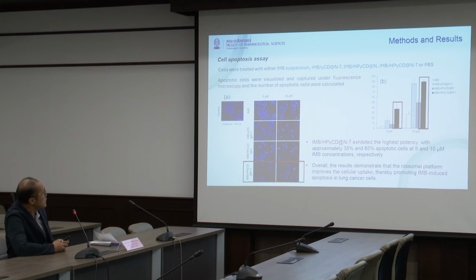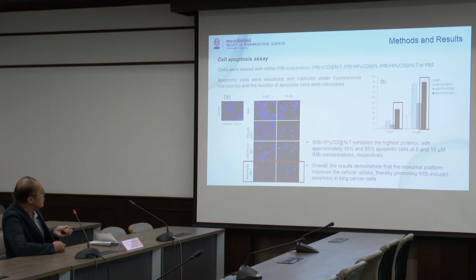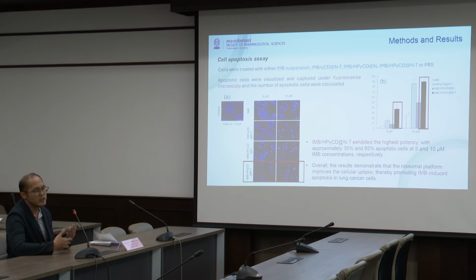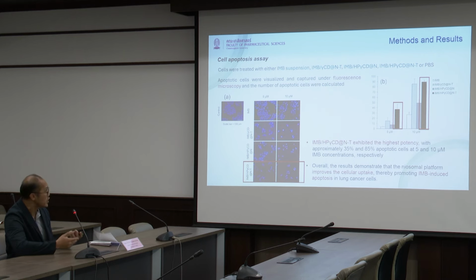And the last one is the cell apoptosis. We can show that in our formulation, especially the niosome with the hydroxypropyl gamma cyclodextrin in the presence of TPGS, it has a high rate of apoptosis compared with the untreated one. It is about 35% when we treat with 5 micromolar and about 85% apoptotic cells when we treat with 10 micromolar. So overall, the results show that we can improve the cellular uptake and promote imatinib-induced apoptosis when we add the cyclodextrin and the TPGS in the niosomes.